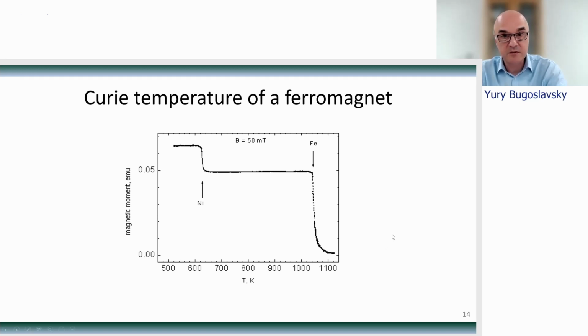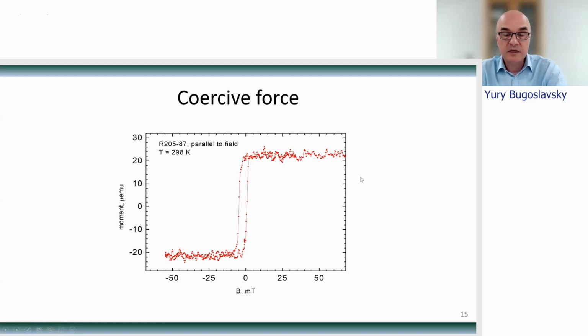The simplest thing we can do is to measure the Curie temperature of ferromagnets. In this graph, we apply a small magnetic field and ramp the temperature to see the Curie transition in nickel at around 630 Kelvin and in iron at 1043 Kelvin. We can take a thin magnetic film and study its coercive force, which is important if you're working on magnetic recording media or magnetic sensors.